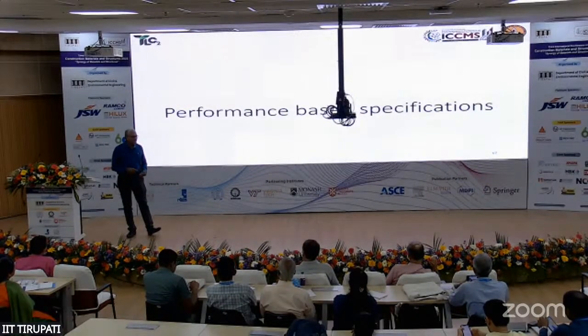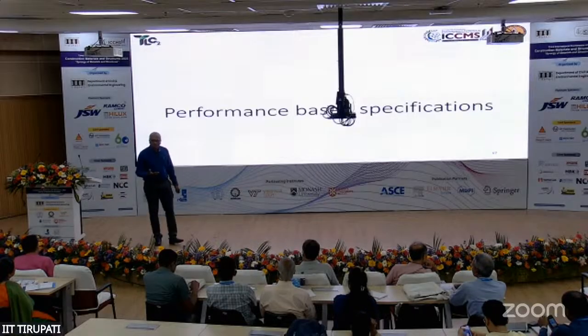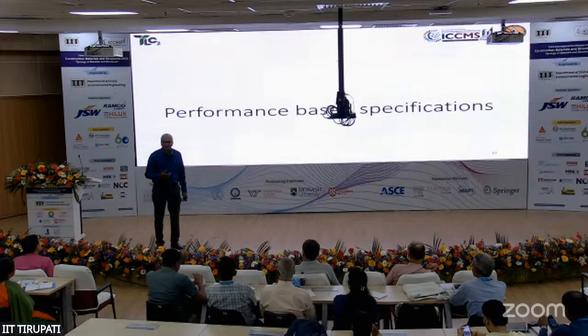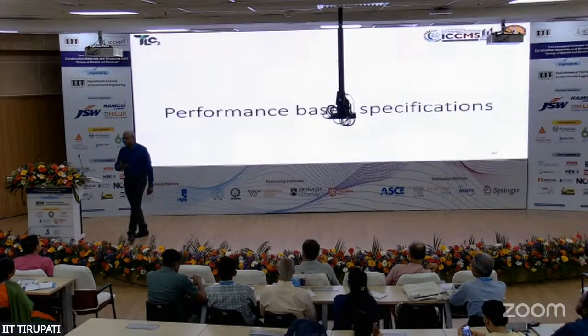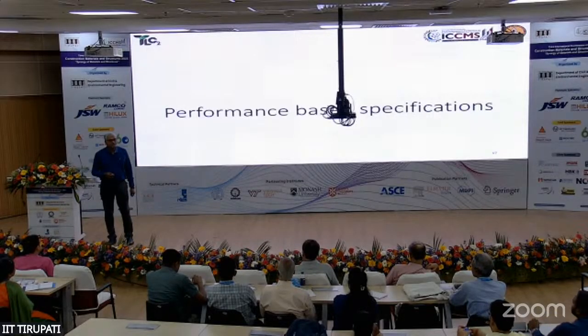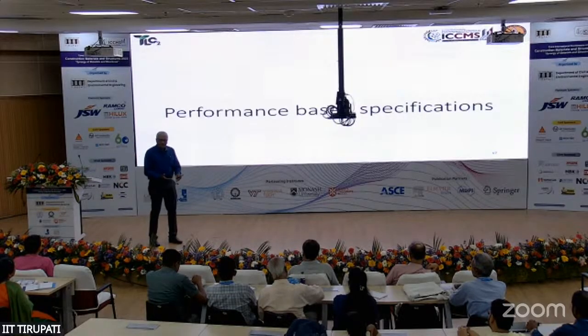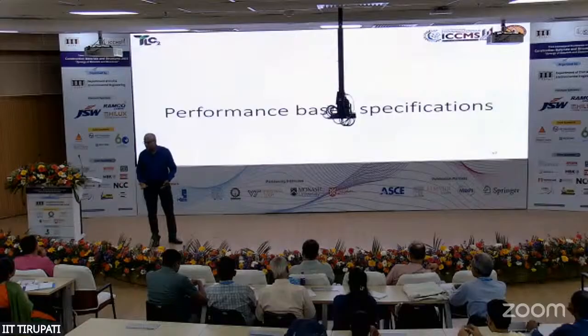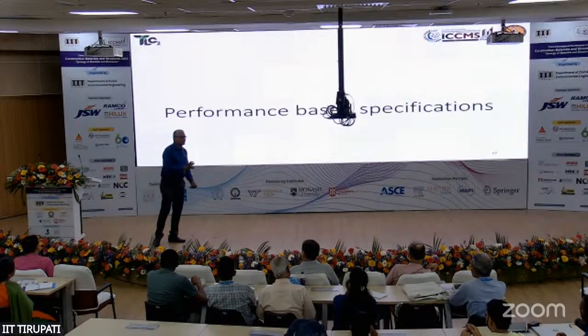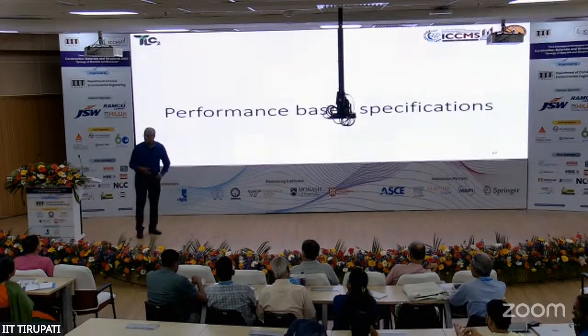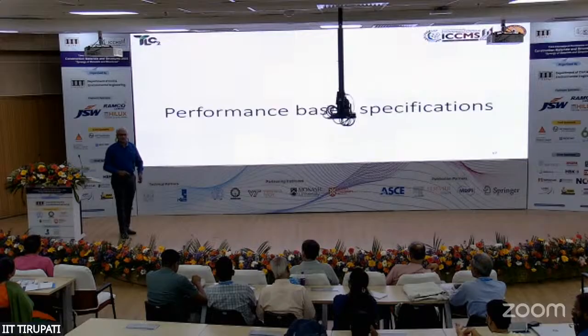Primarily, you can look at simple parameters when the concrete truck comes into your site, is something called a water content determination. Because you know often that to increase the slump at site, a lot of people end up retempering, adding water to the concrete, which is obviously not good because it's going to compromise both your strength and durability, right? Can we have a simple test in which we measure the water content? That could be a simple test that we do on the site. That's a performance specification. Can we write a spec which says when the concrete truck arrives at site, you take a sample and determine the water content? That could be a simple test similar to the electric bulb kind of thing.